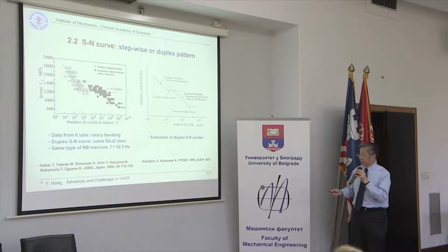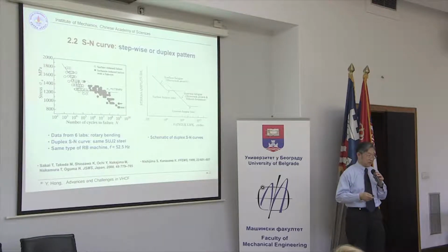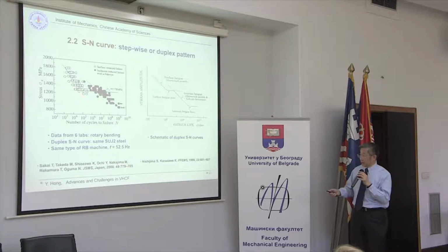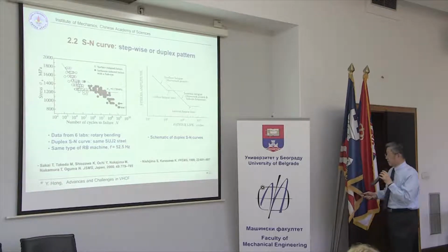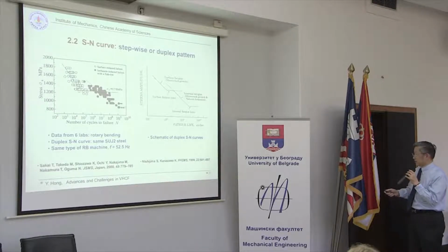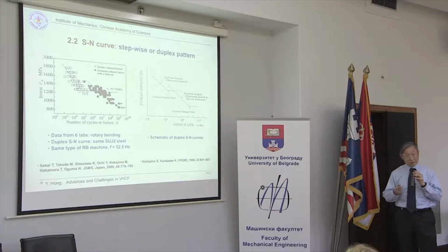And here, they use a type of rotating bending. So that is failure on the surface, and this group is Very High Cycle Fatigue due to internal crack initiation. There's a schematic showing that the S-N curve of Very High Cycle Fatigue is kind of stepwise or duplex. That's a very special, very unique feature of Very High Cycle Fatigue.